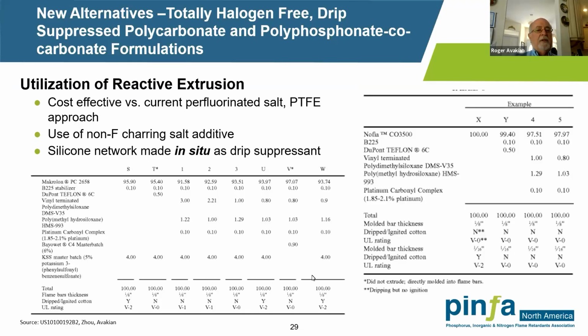This is another thing that was actually done as well. We were talking about silicones, and this was work that was done at PolyOne, now Avient, actually by myself, Zhou, at the time. So again, we mentioned sometimes the difficulty getting silicones into a polymer. In this case, we were basically replacing the perfluorinated strong acid salt as well as the PTFE. And the way to get the silicone into the material was actually making the silicone in situ via reactive extrusion. This worked very well in polycarbonate. There's actually an issued patent in this area, as well as in polyphosphonate co-carbonate formulations as well. So again, a new approach to providing drip suppression. Next slide.